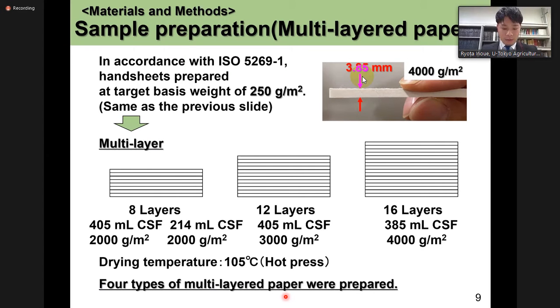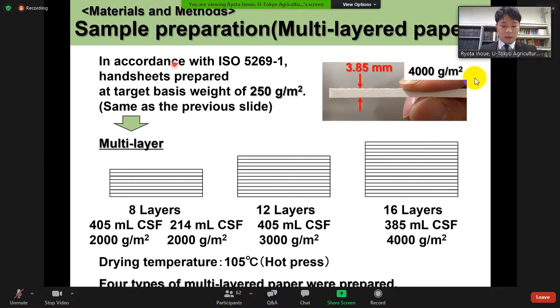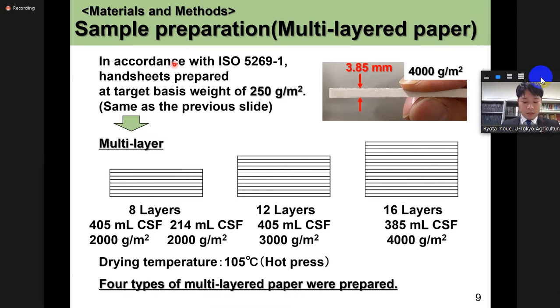Similar to single-layered paper, we prepared hand sheets at a target base weight of 250 grams per square meter. The freeness was 405, 214, and 385 milliliters CSF. We multi-layered this hand sheet in 8 layers to 2,000 grams per square meter for the 405 milliliters CSF and 214 milliliters CSF. In the same way, we multi-layered the sheets in 12 layers to 3,000 grams per square meter for the 405 milliliters CSF and 16 layers to 4,000 grams per square meter for the 385 milliliters CSF.